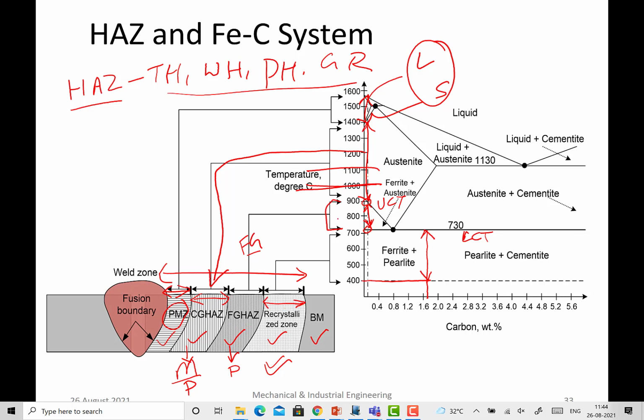If the temperature is limited to 800 degrees centigrade, you may have just a fine grained zone, no coarse grained zone, and a refined grained zone and recrystallization zone. So this is important to be seen.